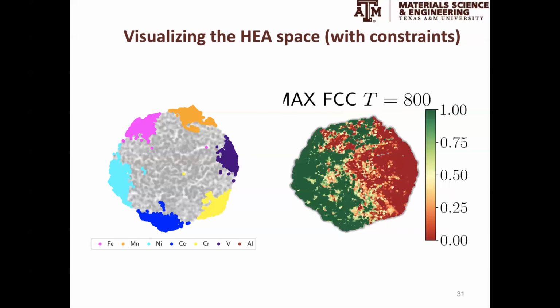Now, when we start to impose constraints, this is what we find. About half of the space, more or less, is actually FCC at 800 Celsius, and not surprisingly this region is centered around nickel and cobalt, and to a certain extent manganese. On the other hand, in the vanadium region, we have alloys that are mostly BCC. So here we have BCC alloys, here FCC, and somewhere in between, in this high entropy or compositionally complex region, we encounter a lot of dual-phase microstructures.